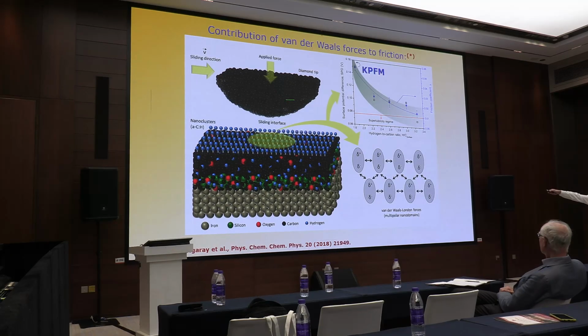Here is the thin film. This is the tip. In this case, we use nanoindentation and sliding, and also AFM to measure the friction forces at the microscale and the nanoscale. And here we have different content of hydrogen. We don't know exactly the quantity of hydrogen. We have the relation between carbon and hydrogen ratio, but we don't know the hydrogen content at the surface. But we know that we have more or less due to the carbon-hydrogen ratio.